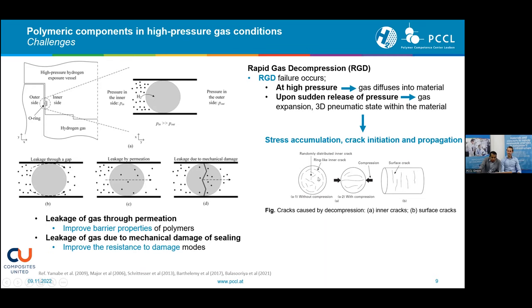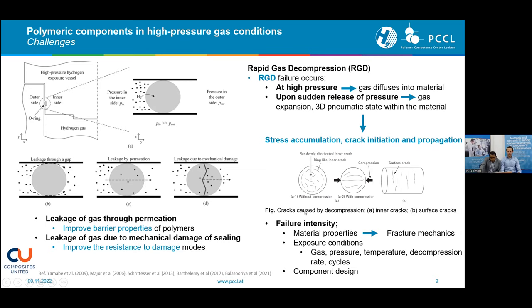So if it was without the compression, these cracks could be just randomly distributed, or if it's stressed, like in a real application, then these cracks could align. So if these stress levels are even fatal, then cracks can go on to the surface of the O-ring. So this failure intensity also depends on the material properties.